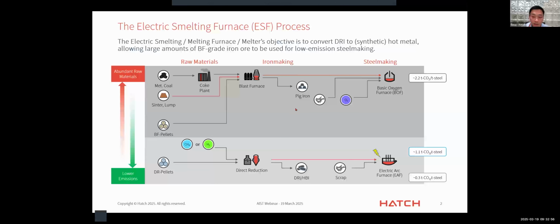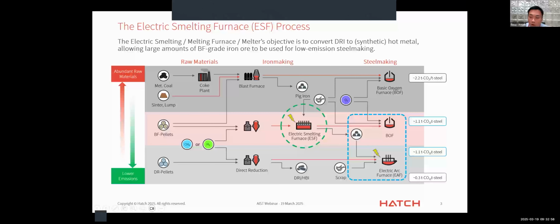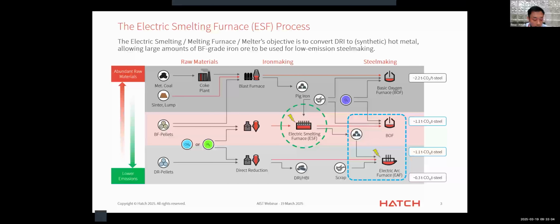Where the ESF fits in is sort of a third way, the middle path. It is using widely available, typically BF grade iron ore. Today it's mostly in the pellet DRI form, but certainly sinter fines and fluidized bed based ironmaking processes are compatible as well. And using an electric smelting furnace, or smelter, or melter, or electric melting furnace, turning into hot metal, or in this case, sometimes we refer to it as synthetic hot metal, or sometimes called green hot metal, for use downstream in steelmaking.